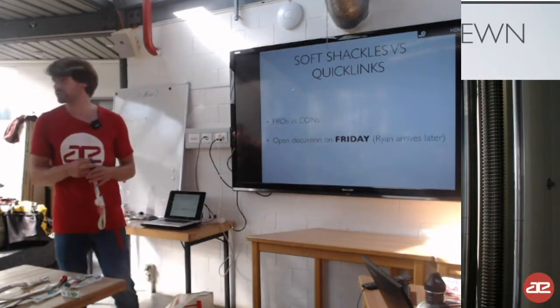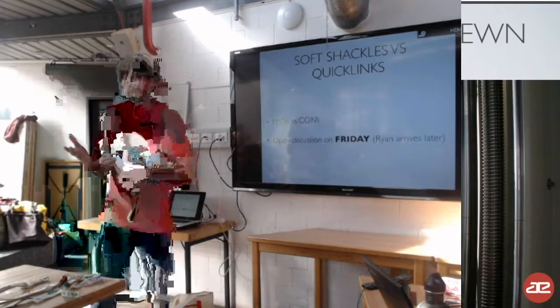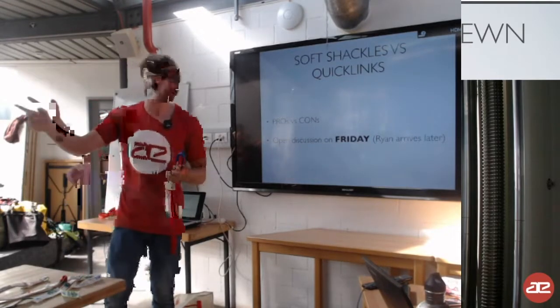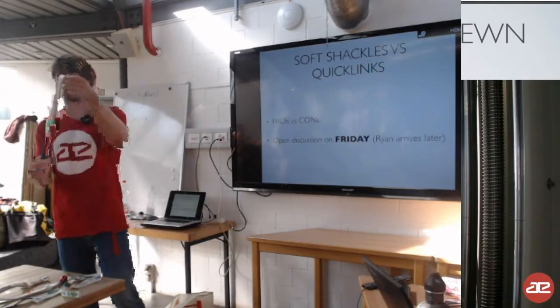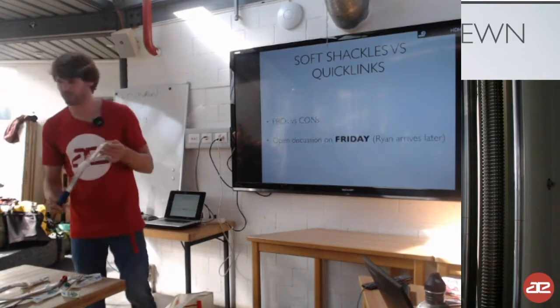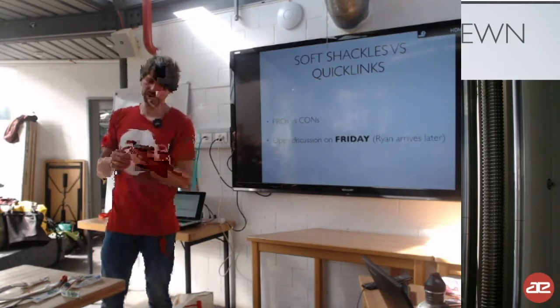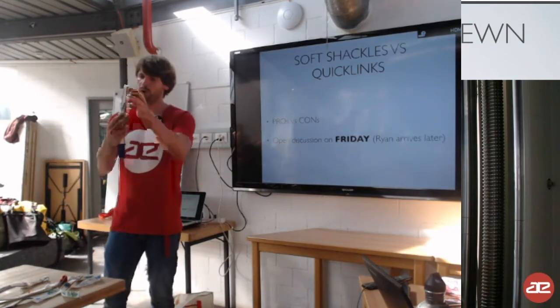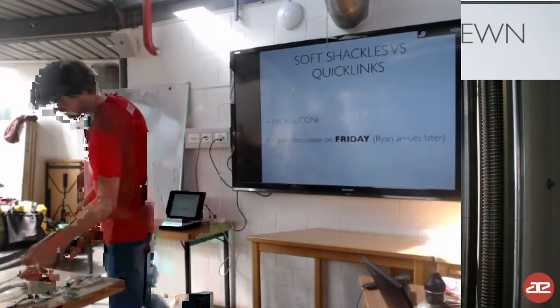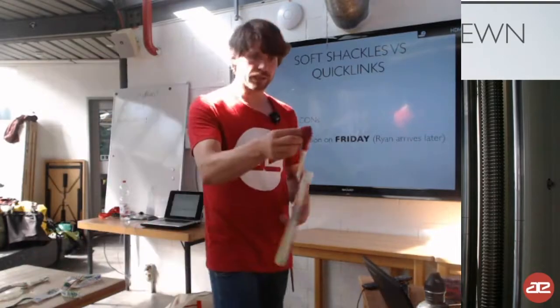Normally we could see this in the slides now as a video. I'm sorry, this must have gone missing somewhere in the transfer of the presentation between my laptop and this laptop. This is the piece that was tested with a padded loop and a padded soft shackle down here. The soft shackle was padded with the same webbing too. And here finally the webbing broke where it's supposed to break, in the stitching part, so the webbing itself gave up. We did this test multiple times, so you can see this result is repeatable.